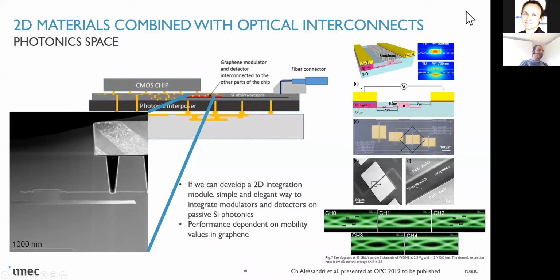Just to continue towards optical interconnects, this is a kind of vision that we have, but we are also working, and basically we have integrated that already on 300 millimeter, to make graphene-based modulators and graphene-based detectors integrated in a CMOS flow, and you can immediately see that we did that towards a Damascene module. So this has nothing to do with the lift-off processes that are typically from the lab. We are still fine-tuning, we are not fully there, but this is the vision on how you could in a simple layer integrate active components on passive waveguides.